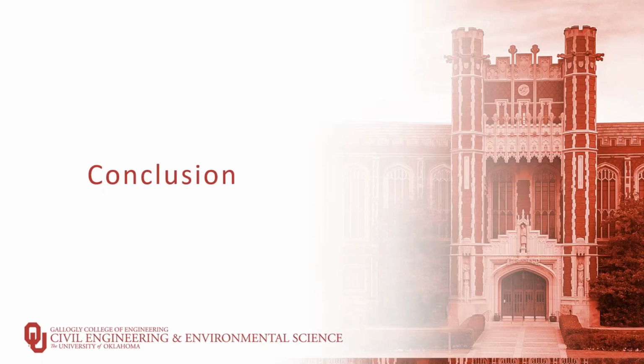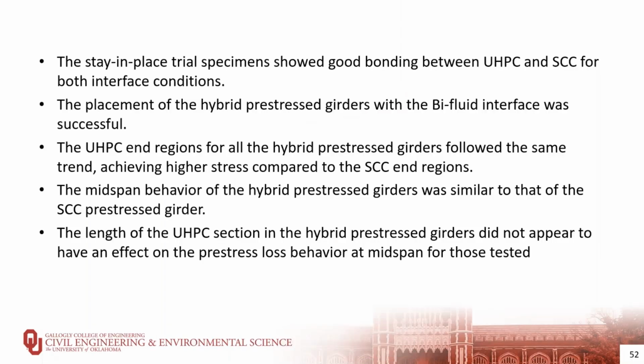In terms of conclusions, those are the preliminary conclusions that we achieved from this study so far. The stay-in-place trial specimens showed good bonding between UHPC and SCC for both interface conditions. The placement of the hybrid prestressed girders with bifluid interface was successful for all the specimens. The UHPC end regions for all the hybrid prestressed girders followed the same trend, achieving higher stress compared to the SCC end regions.